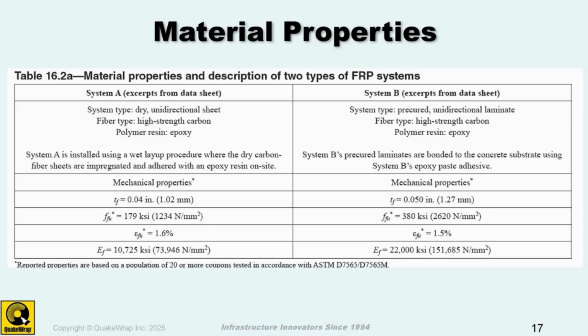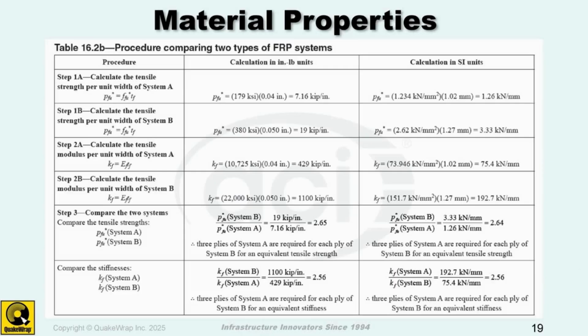These, as you can see, they get much higher. Like the tensile strength is 380 ksi versus the one that you make in the field, which may be about 170 or 180 ksi. And the modulus of elasticity likewise. For the ones that are made in the field, they are lower. When you make it in the factory, the modulus of elasticity is almost double the other one. So just keep these things in mind as you do that.